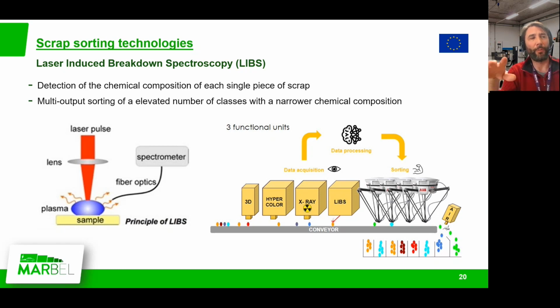So you have a conveyor, generally a belt conveyor. You measure the chemical composition. With cameras, you position this particle in the belt conveyor, and then with a robotic arm, you place it in the class of scrap that fits better with this chemical composition. With that you can have several scrap classes with narrower chemical composition.